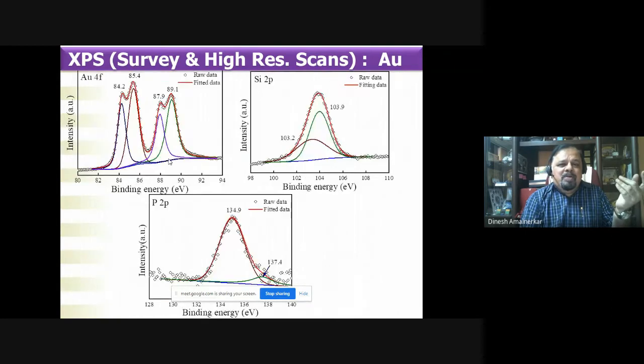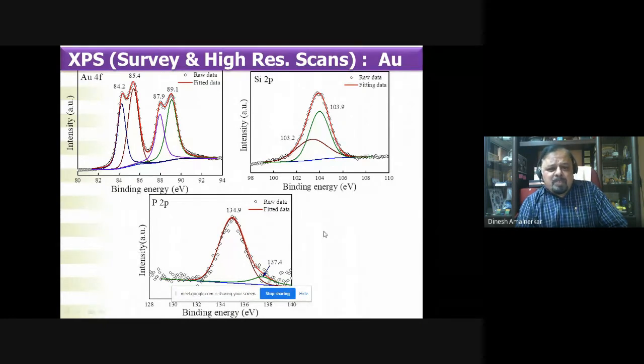So this is gold. Now you look at the Au 4f core level of gold. There is a doublet structure, and after deconvolution, you can see the two properly deconvoluted peaks. What we can see is that the peaks at 84.2 and 87.9 electron volts belong to metallic gold, and 85.4 and 89.1 electron volts probably belong to a kind of oxide between gold and oxygen. So this is a very important clue. We really didn't bother about silicon and phosphorus at the moment.